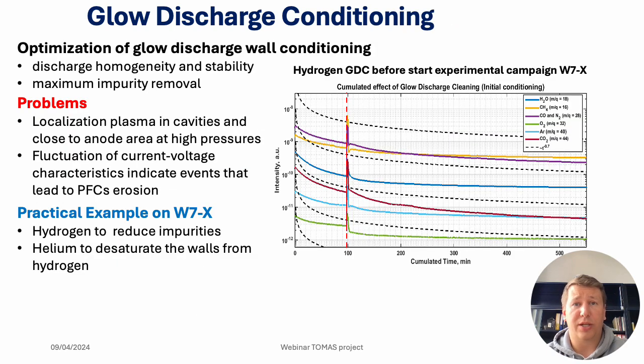The glow discharge optimization also requires improvement of glow discharge homogeneity and stability. It means that the discharge should not be localized in any vessel structures, and the current-voltage characteristic should not contain any oscillation, to prevent arcing. Moreover, the working gas plays a significant role in glow discharge cleaning optimization. Hydrogen is more suitable for impurity removal.